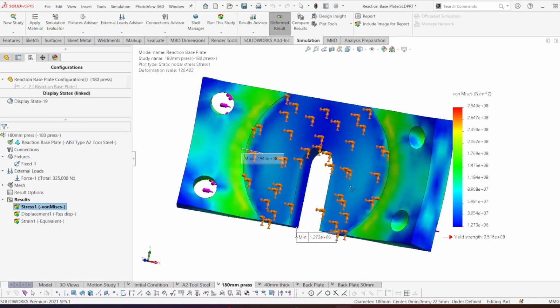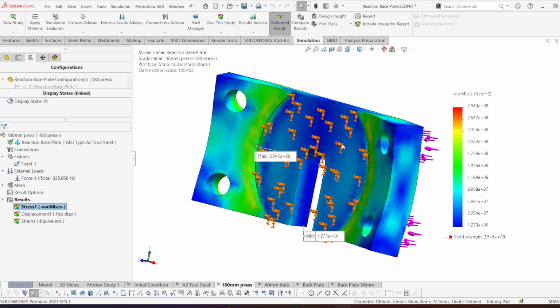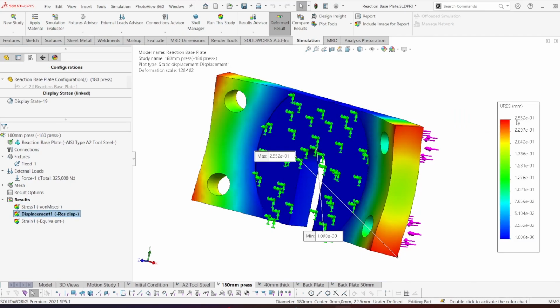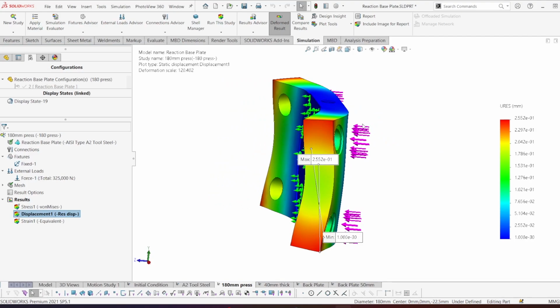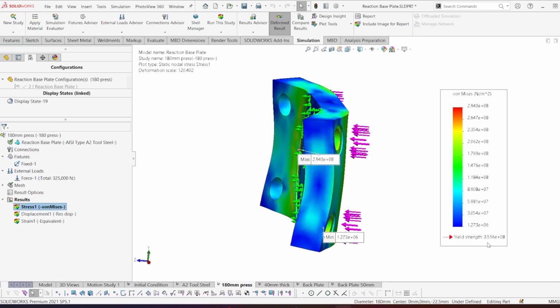So at 180 mm spacer between the hydraulic press and the back plate here, we can see immediately that the stress has already gone down to 284 megapascals, which is less than the yield strength of tool steel, which is about 350. So this is already a good result without changing material. Displacement is now at 0.25 mm, which is negligible, and because the stress does not exceed the yield strength, this would spring back into its original condition.